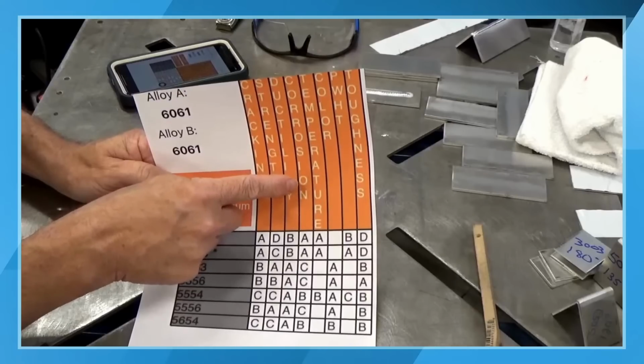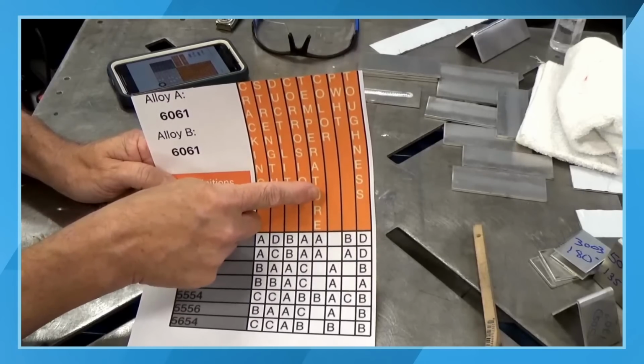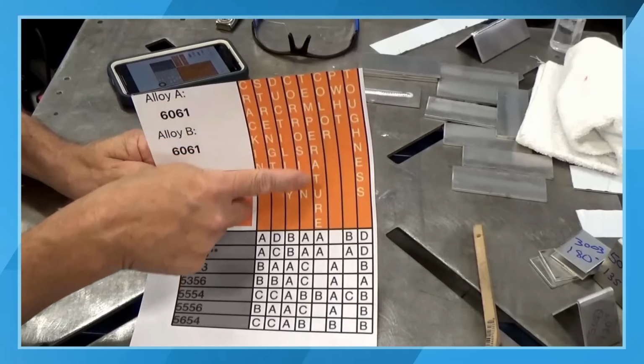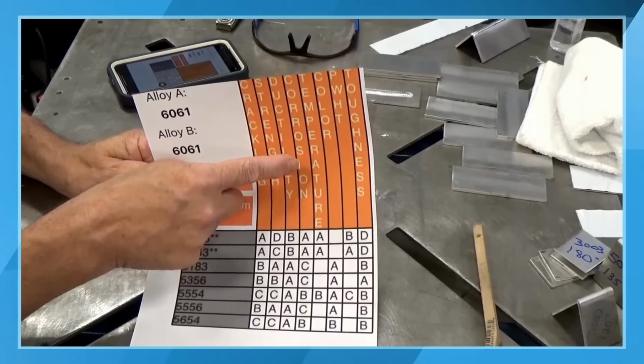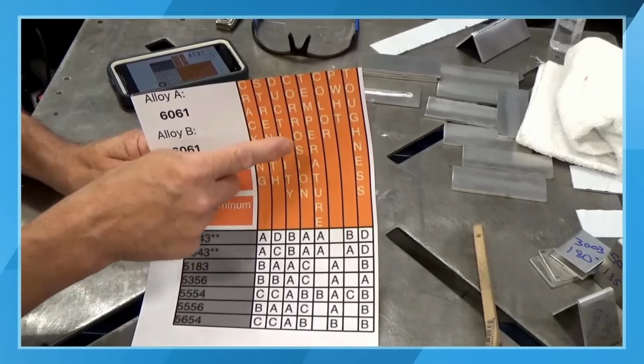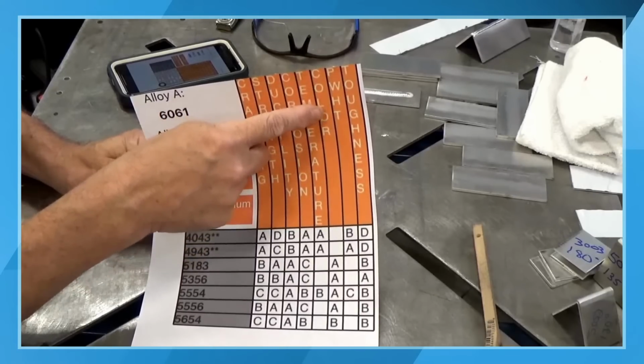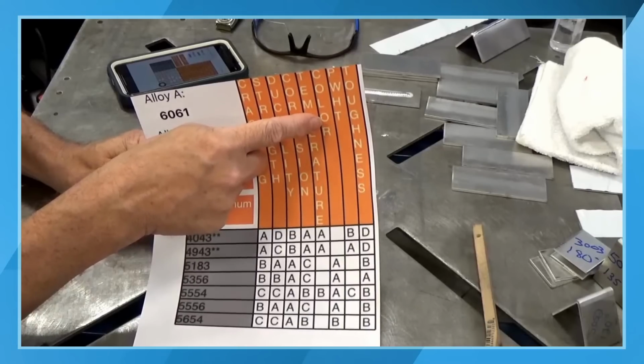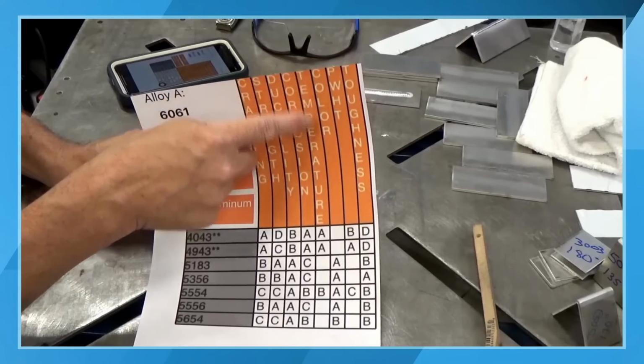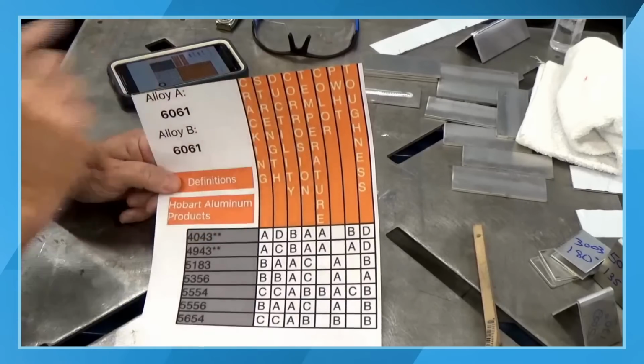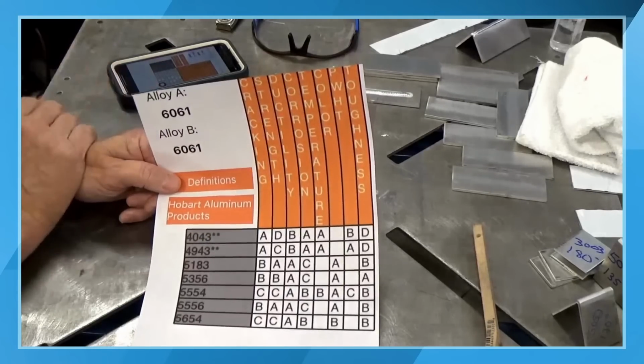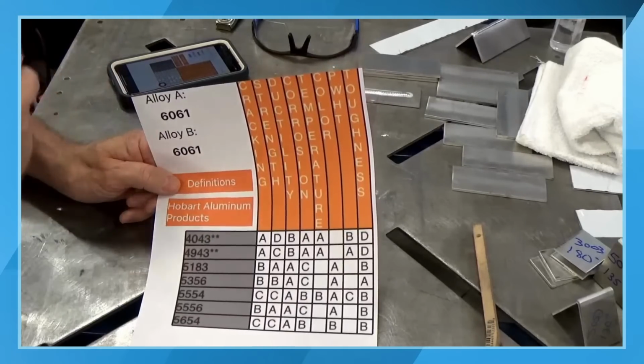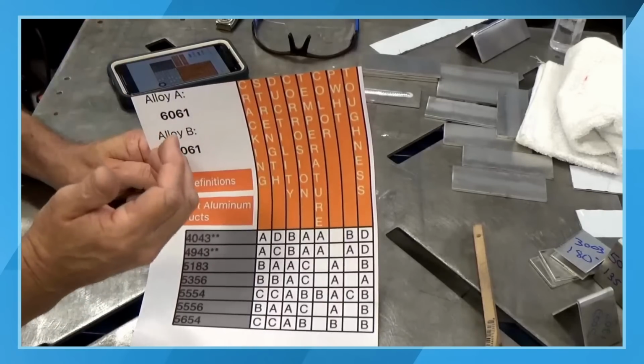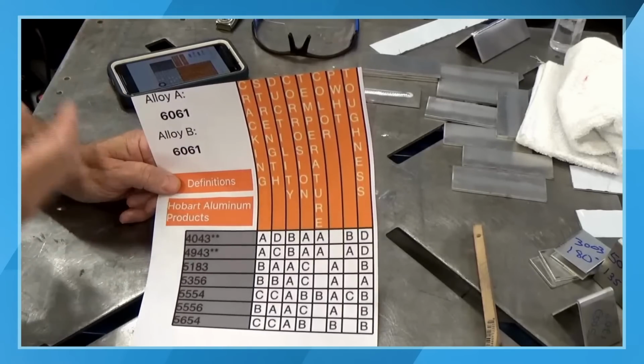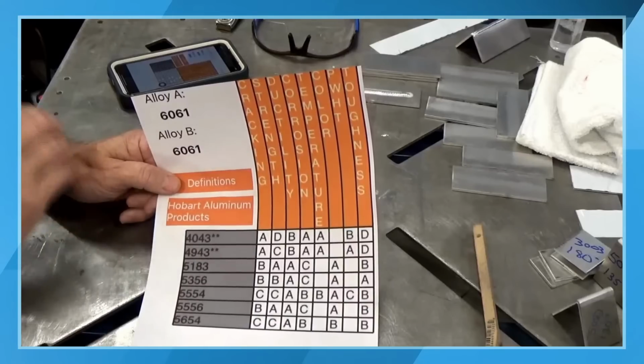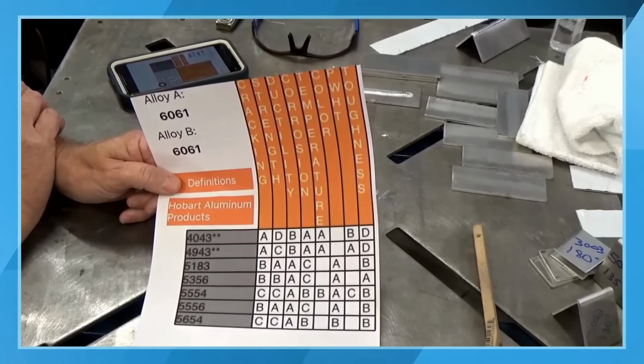Corrosion, basically that's if you're in an environment where it needs to be resistant to both fresh or saltwater corrosion. Temperature, this is where we talked about being in a high temperature application, anything over 150 degrees F. Color match, now that's not the color of the weld puddle or the weld bead after you're welding it. That's going to be color matching if you're talking about doing any anodizing afterwards. And you want to make sure that the weld bead is going to anodize at the same color or similar color as the original base metal.